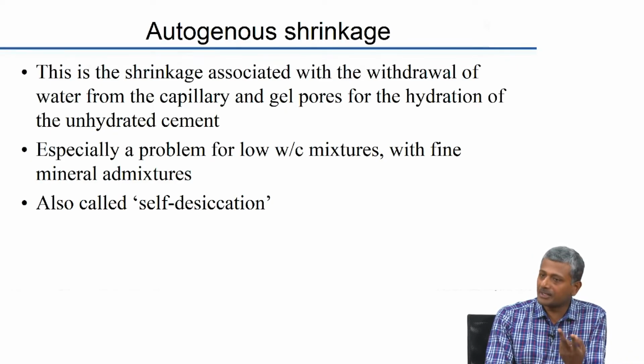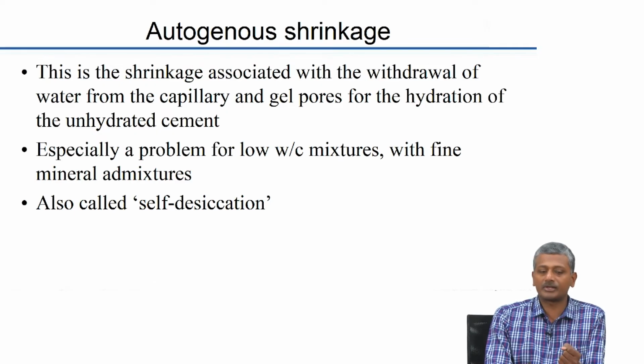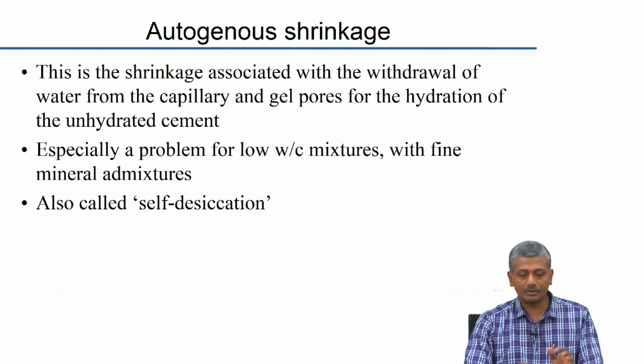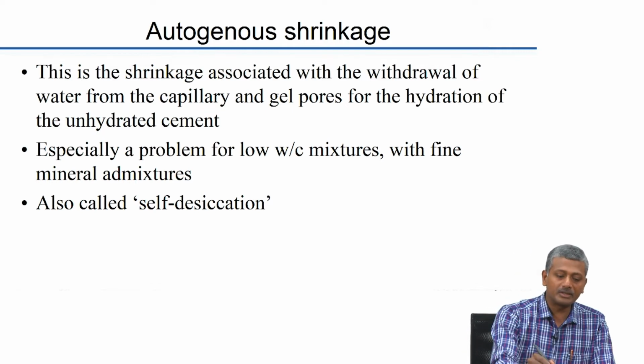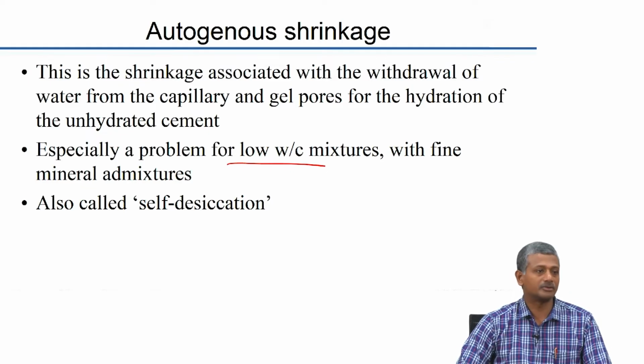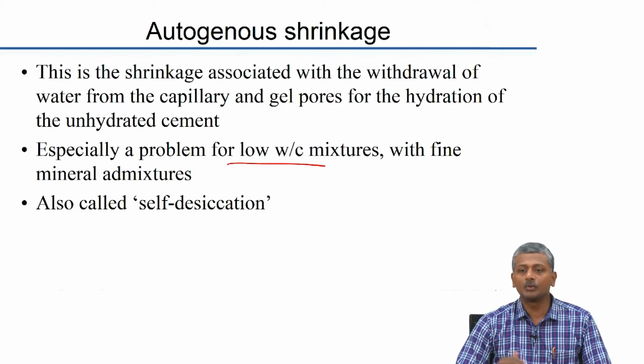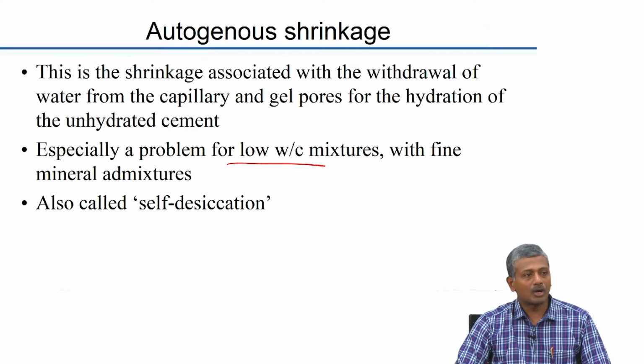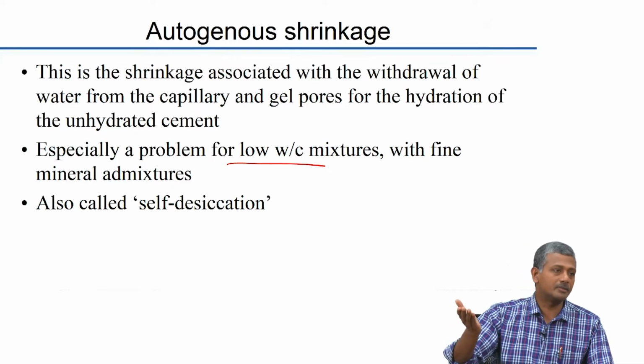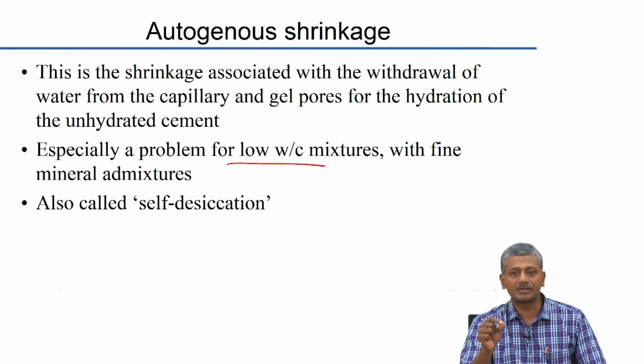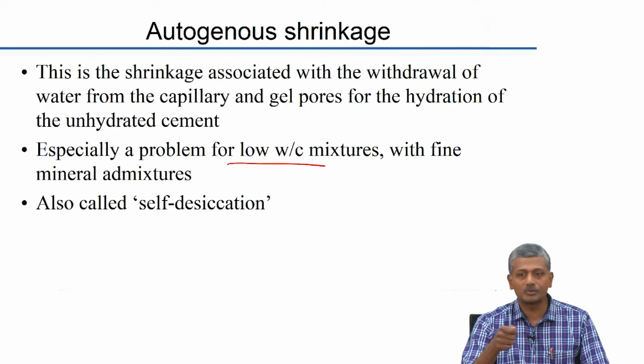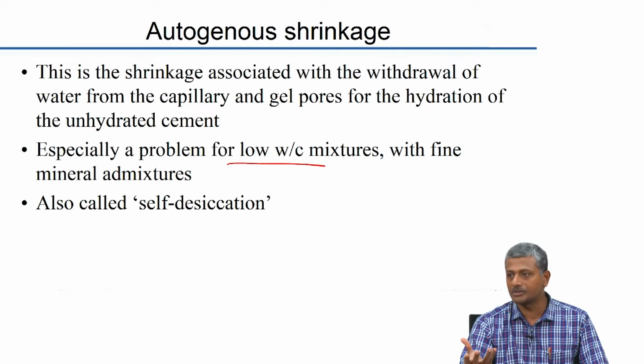Okay. So, there are basically two components, one is the movement of water through thinly constricted capillary pores and the other is the formation of hydrated cement paste which results in a reduction in volume. Okay. So, essentially autogenous shrinkage is a little complex because of that, but it is generally a problem primarily for low water cement ratio mixtures, right, because you can imagine when you keep on reducing the water to cement ratio, what happens to the level of unhydrated cement in the system? It goes up. Low water cement ratio, more unhydrated cement. Another factor is low water cement ratio also means that the pore sizes are smaller. If the pore size is small, then the travel of water through these pore sizes will be generating a lot higher capillary pressures that will lead to more shrinkage.